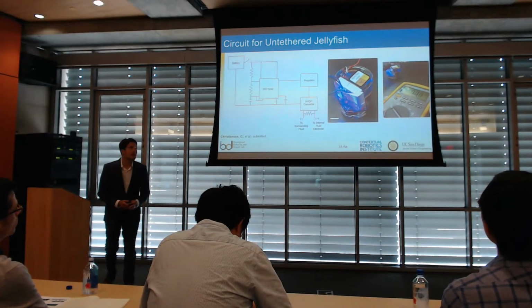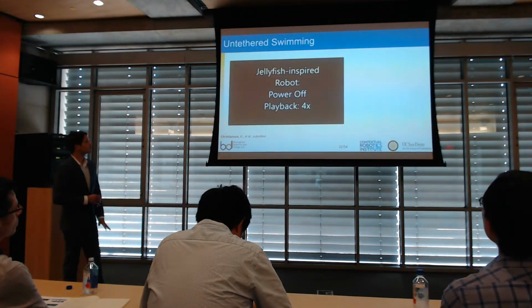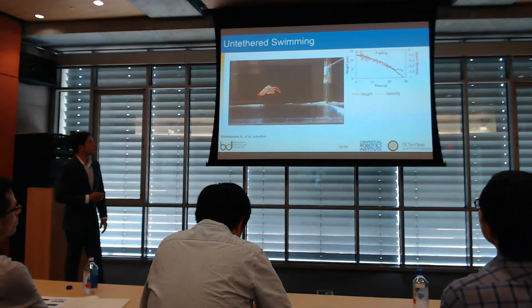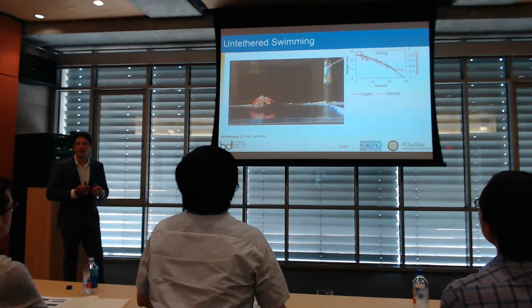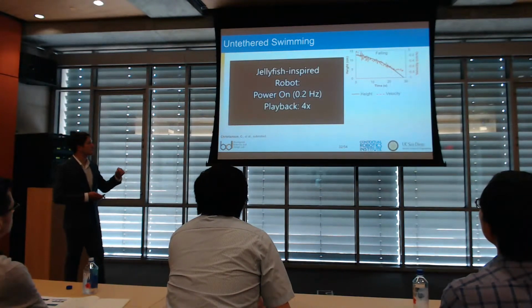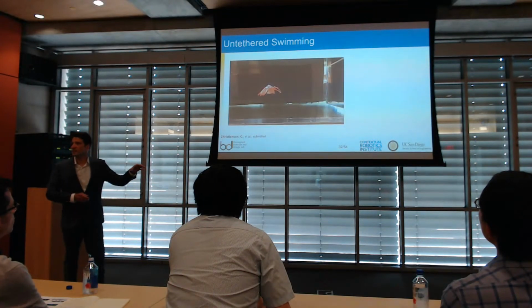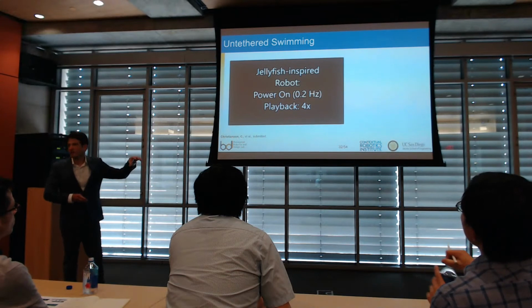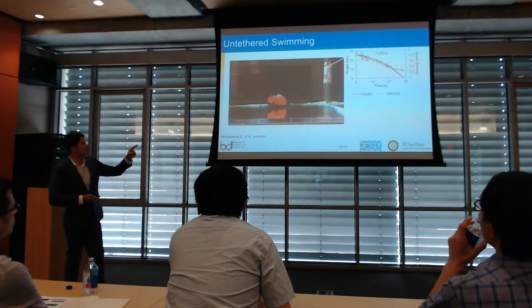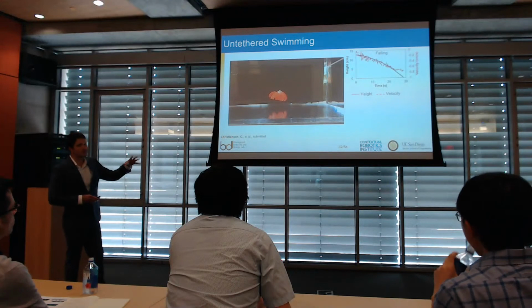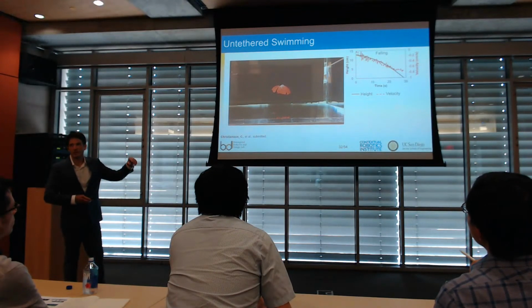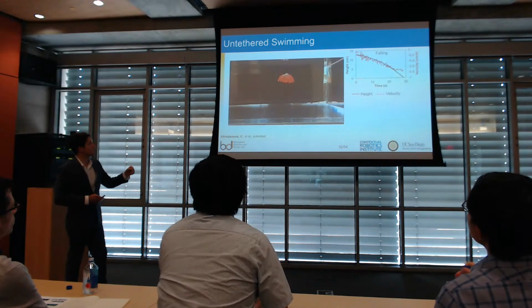So we wanted to show we could connect this to the rest of the robot and get it to swim untethered. So here we are. One of the challenges with swimming with soft robots is that it's very easy to get it to float because of buoyancy. And so what we did is we first made it slightly negatively buoyant. So we added an air bladder on the top of it to offset the weight of the electronics, but made it slightly negatively buoyant so it falls. And then that's this bladder on the right. And then once it fell to the bottom of the tank, then we turn it on and get it to swim upwards. So this is at 4 times speed as it's swimming.